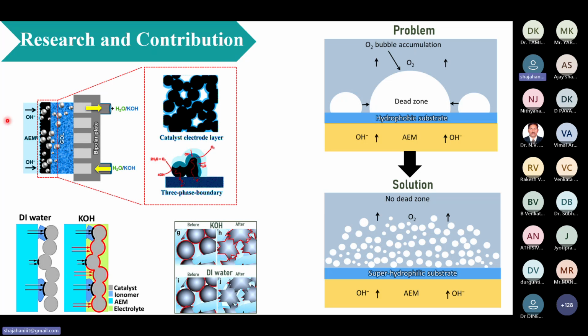In the electrolyzer, when water electrolysis happens, the oxygen evolution reaction or hydrogen evolution reaction occurs on the catalyst layer. If the bubbles are released freely from this interface, then no problem. We can use the catalyst effectively, the AEM membrane lifetime will increase, and we will get the production rate. But this is not the case, because most electrolyzers use a hydrophobic substrate as catalyst support. On this substrate, they deposit or load the catalyst layer, and directly use it in the electrolyzer.